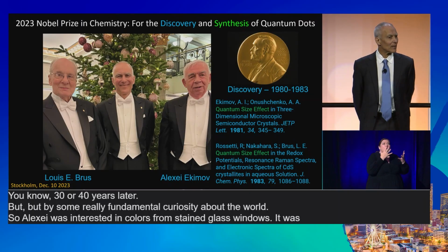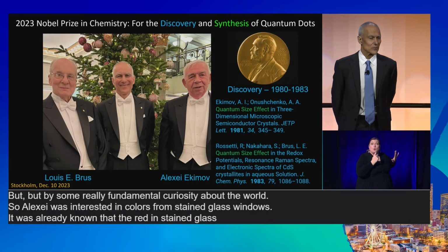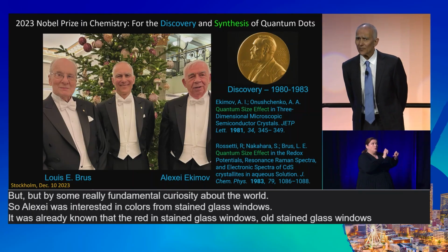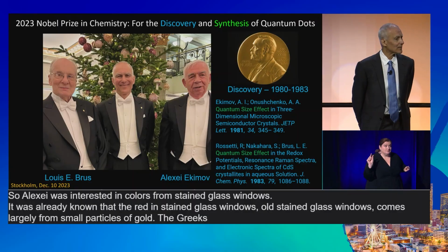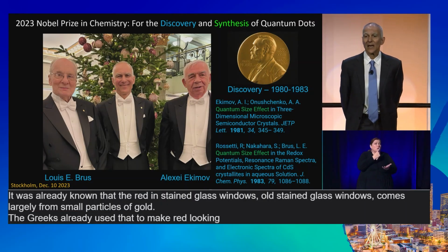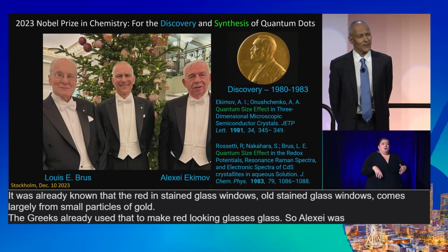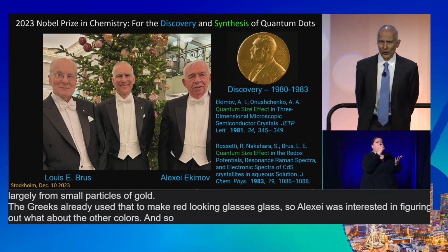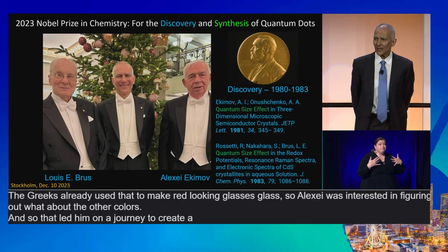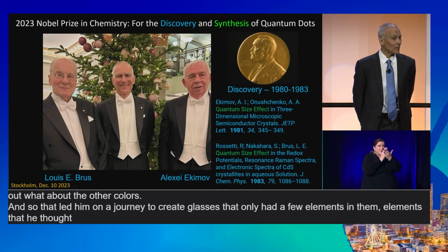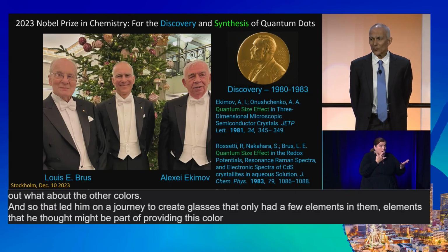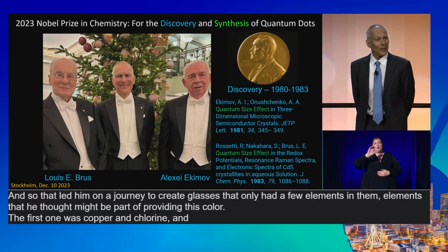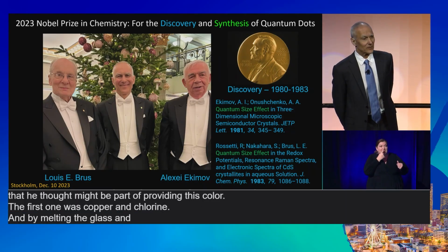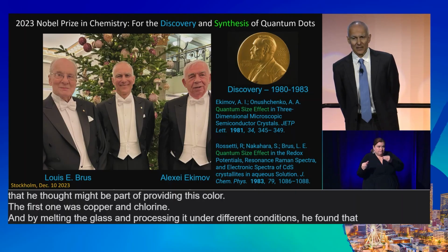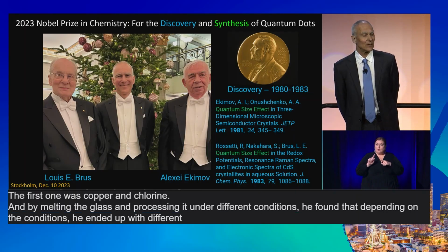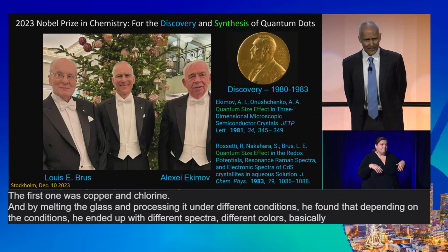It was already known that the red in stained glass windows, old stained glass windows, comes largely from small particles of gold. The Greeks already used that to make red-looking glass. So Alexei was interested in figuring out what about the other colors, and so that led him on a journey to create glasses that only had a few elements in them, elements that he thought might be part of providing this color. The first one was copper and chlorine. And by melting the glass and processing it under different conditions, he found that depending on the conditions, he ended up with different spectra, different colors, basically, but with the same elements in there.